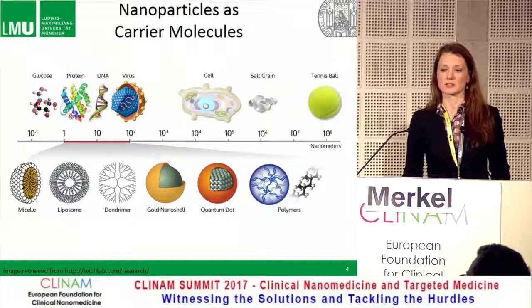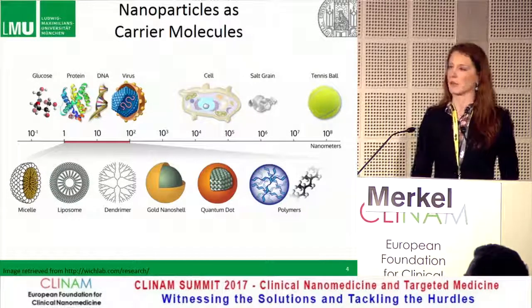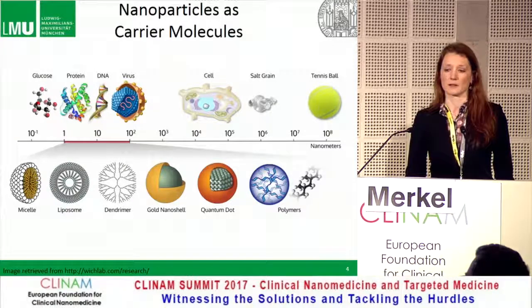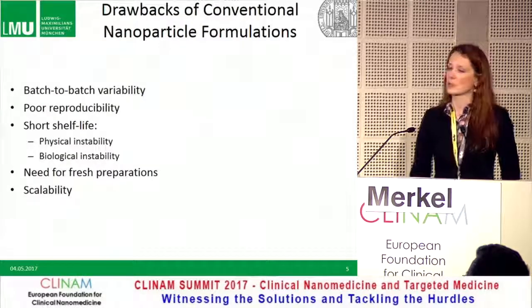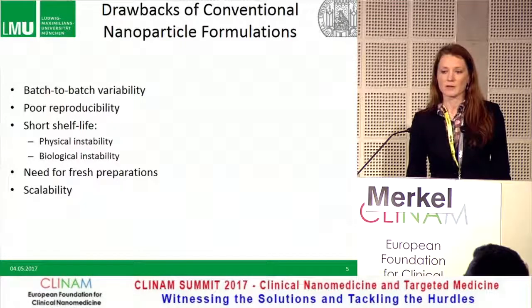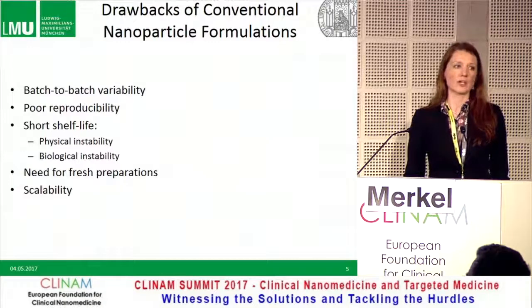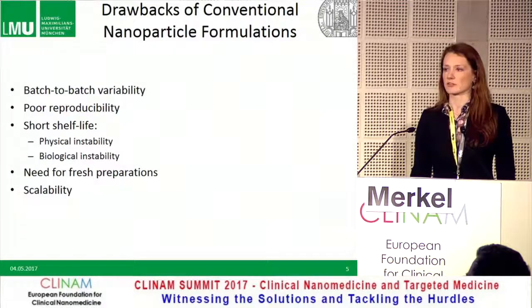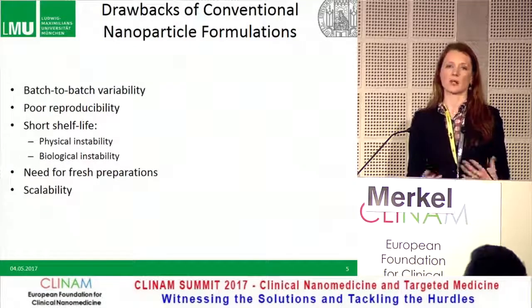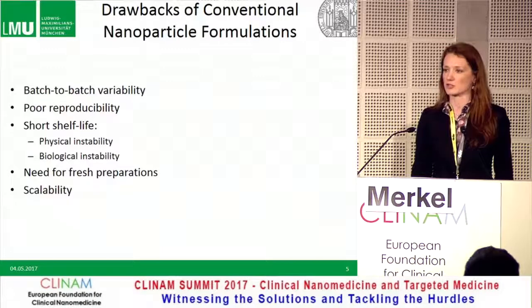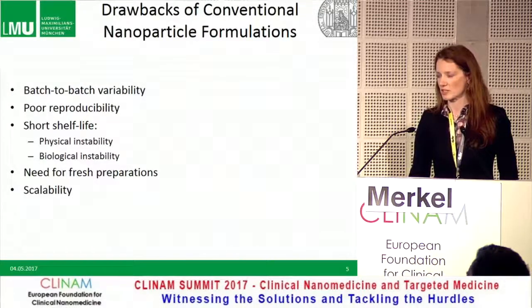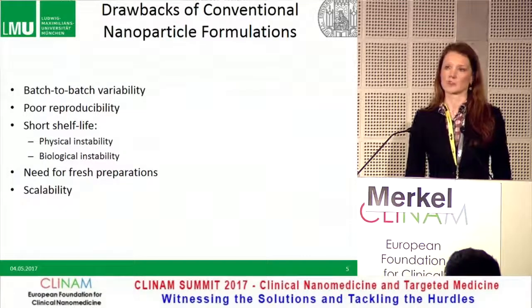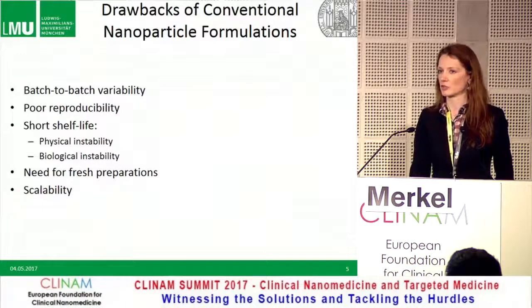There's a broad range of different nanoparticle carriers for nucleic acids. I will focus in my talk on micelles — specifically, we use block copolymers rather than the typical phospholipids. The big drawback in conventional nanoparticle formulation is that we do it on a lab scale and have big differences from batch to batch. Every time we make a new batch, sizes, polydispersities, and zeta potentials can be quite different — or a new student may produce different results. Overcoming this batch-to-batch variability would really help in the clinical translation process.